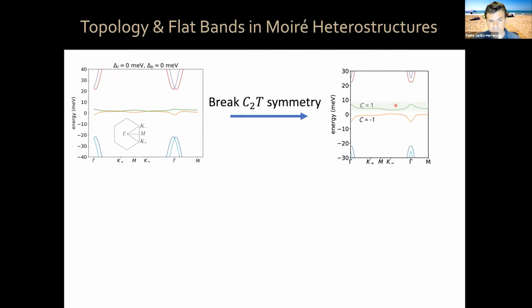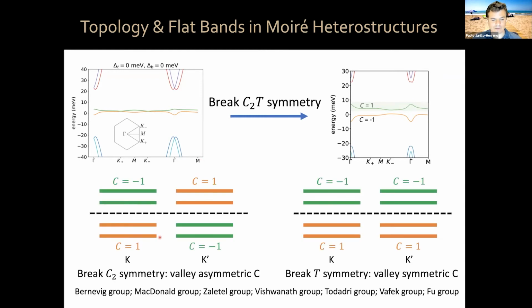Now you can do this in various ways. For example, you can think, let me break the C2 symmetry. Then you have a set of bands with Chern numbers, where there is a valley asymmetric Chern number between the K and the K prime valleys. You can break time reversal symmetry instead, and then you have a valley symmetric Chern number situation. Part of the complexity and the richness of the system has to do with these different possibilities and with interactions leading to small symmetry breaking terms that can lead, through interactions, to breaking of degeneracies.